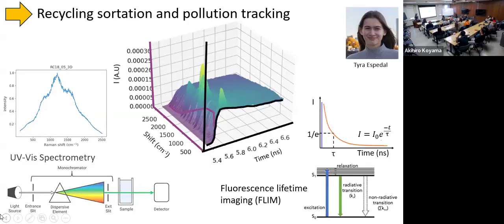And if we go to our other orientation, this in principle should be our fluorescence lifetime decay that you use another very expensive and quite rare instrument to collect, which gives the decay profile of these fluorescence photons. So what we have been working on this summer and into the school year is trying to validate the time-gated Raman for extracting these fluorescence and lifetime profiles from our measurements. So it would be a 3-in-1 where we can get Raman spectroscopy, UV-Vis emission profile, and fluorescence lifetimes all in one measurement that notionally takes less than 30 seconds.